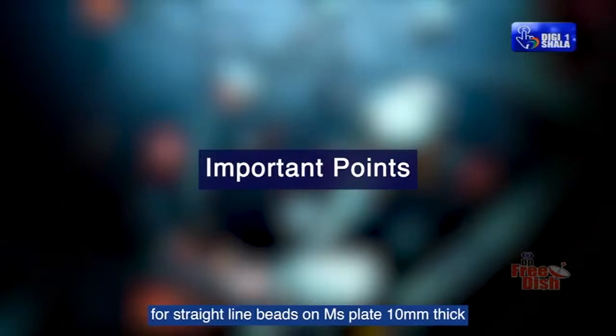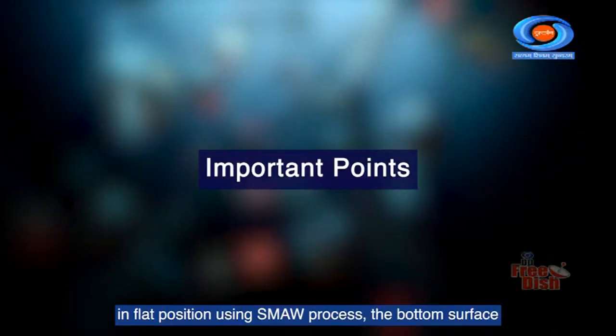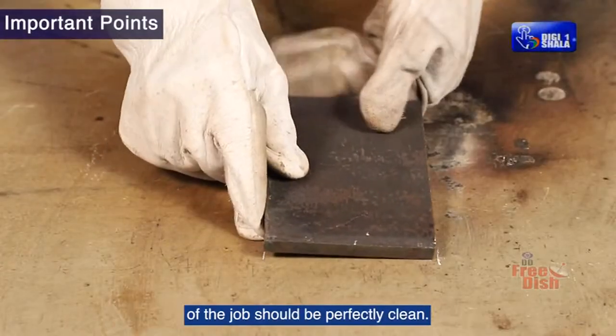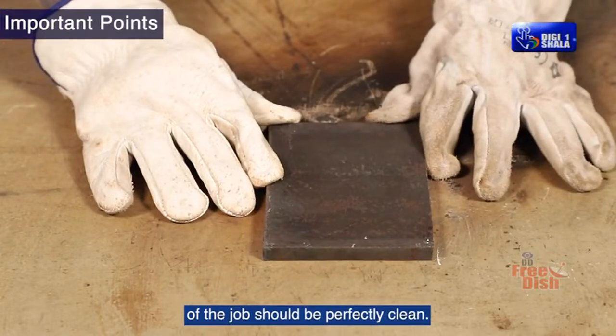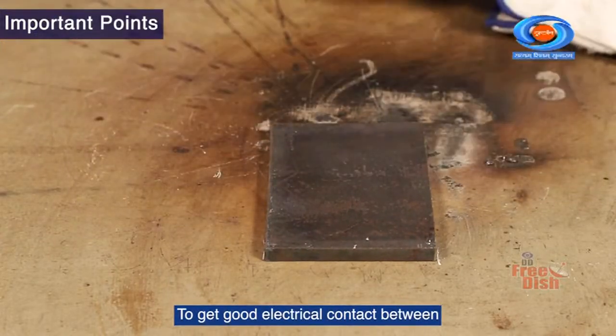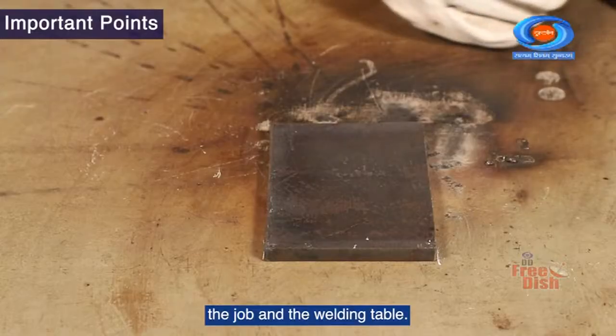There are some important points to be followed for straight line beads on MS plate 10 mm thick in flat position using SMAW process. The bottom surface of the job should be perfectly clean to get good electrical contact between the job and the welding table.